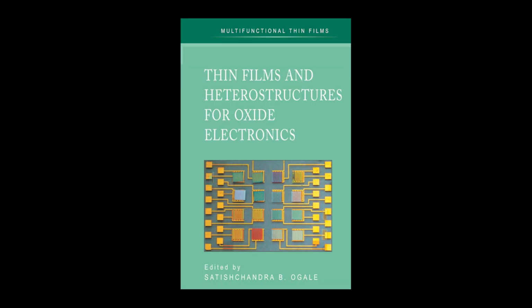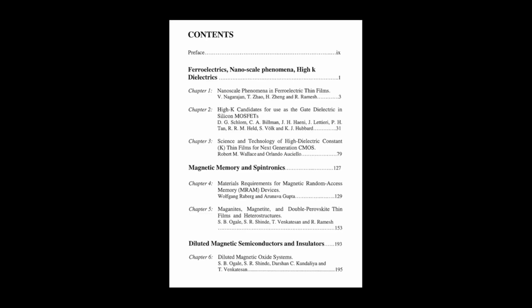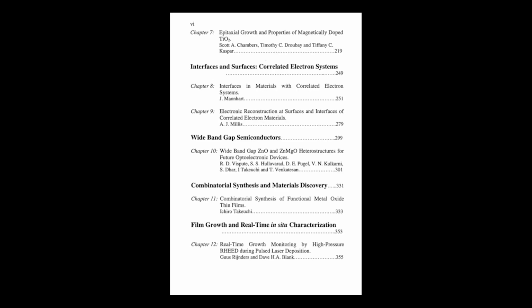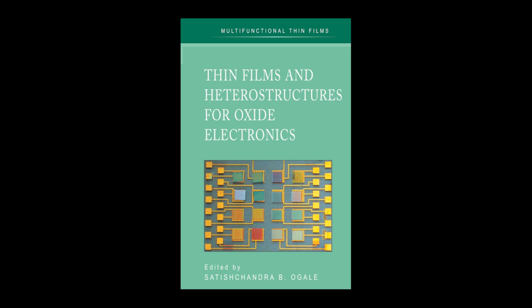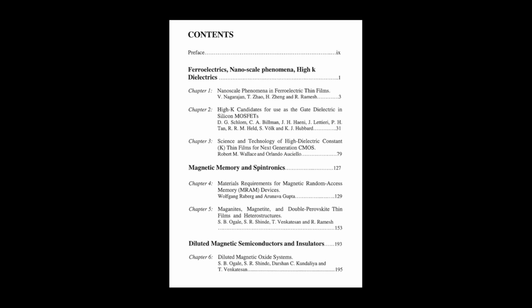Success is measured by how well you can control atomic disorder, especially at those critical interfaces. And when you look at the materials that consistently popped up as the most promising things, like lanthanum aluminate, LaAlO3, for dielectrics, bismuth ferrite, BFO, for ferroelectrics, the manganites for spintronics, they're often these complex perovskite oxides. Structures known for being incredibly sensitive to stoichiometry, strain, defects, those interface effects we discussed. Right. They offer amazing potential functionality, but maybe they come with an inherent fragility.